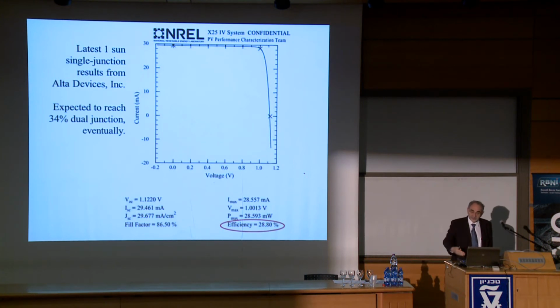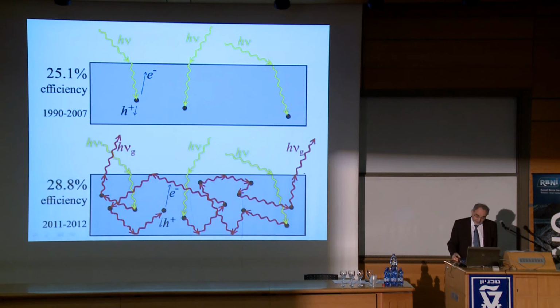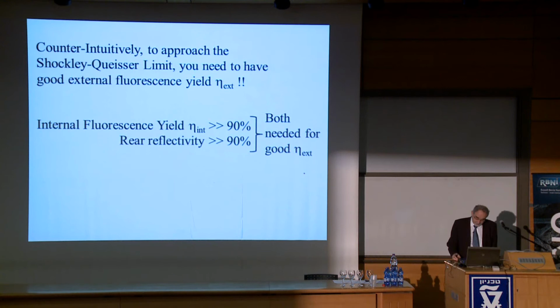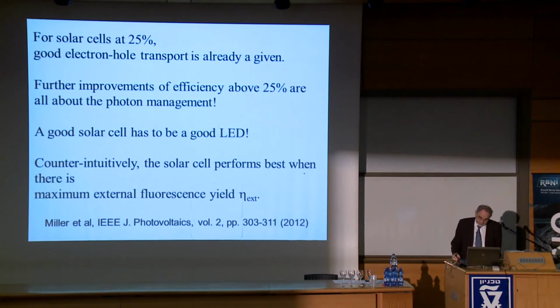They went from a 96% mirror, and they broke the record. Then they went to a 97% mirror, and they broke the record again. And a 98% mirror, that's approximately what you have here. So they kept breaking the record just based on improving the optics. In effect, they went from this situation to this situation, and the more closely they got into this regime, the higher their record was. Both are needed, of course. You need high internal fluorescence yield and high reflectivity.